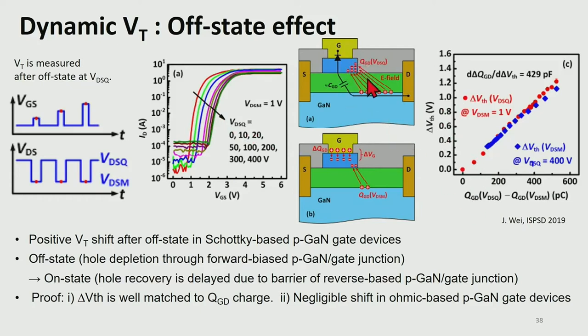So what happens is during the off-state, this P-GaN and the channel junction is reverse biased. So holes in the P-GaN region are depleted and they can escape the P-GaN through this top Schottky junction. But once the device comes back to the low voltage state, now the holes have to come back to the P-GaN, but it takes time because now they have to go through this reverse bias Schottky junction. And this delay caused the hole deficiency in the P-GaN and caused the positive VT shift. So as you can see in these studies, the P-GaN gate can have various dynamic VT shift behaviors. And these effects need to be considered in the device design and also circuit design.